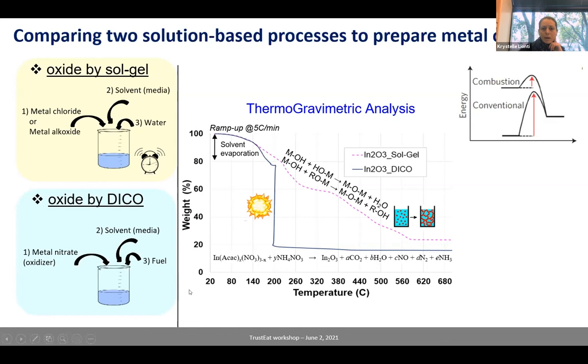And so if we ignore the little bit of solvent evaporation that we have in the beginning, what we see really is that for the Sol-Gel system, as we provide more and more energy to the system, we are forming our oxide network. And when we reach about 600 degrees Celsius, we see no weight loss anymore, indicating that we have fully converted our system to our oxide.